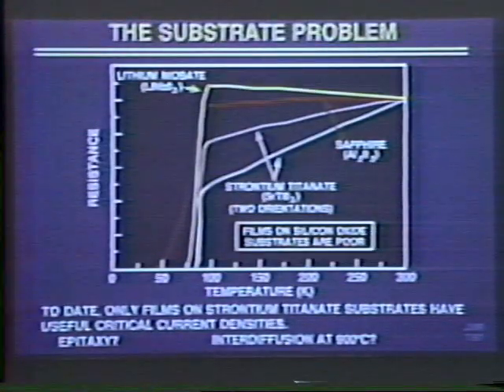This is the substrate problem. Here I show the resistance versus temperature for a number of films which we made using this laser deposition technique on various substrates, strontium titanate, sapphire, and lithium niobate, and let me tell you that the ones on silicon oxide were so much worse than this that we don't even have them on the view graph. Now you can see that the only films which have a high TC are the ones put down on the two orientations of strontium titanate, even though each of these films was put down, as much as we could tell, under the same conditions and had the same heat treatment, in other words, put down at 500 and heat treated to 900 afterwards.